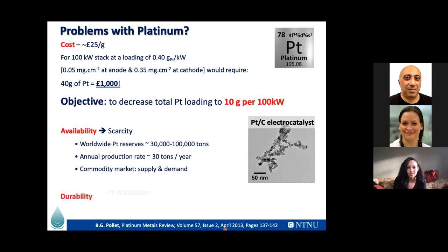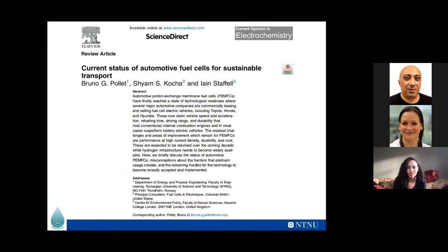There's also platinum dissolution, especially when you're cycling your fuel cell at different potentials, high potentials. You get aggregation and sintering, but also you've got carbon corrosion happening quite a lot. Okay, so for those who are interested, this was published in 2019, I think, and I could send you the link. It's quite an interesting paper looking at the myths around platinum and its availability, etc.